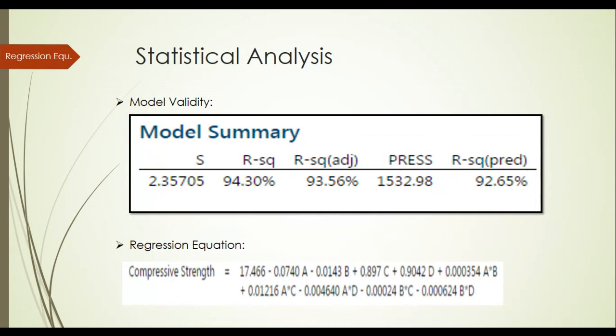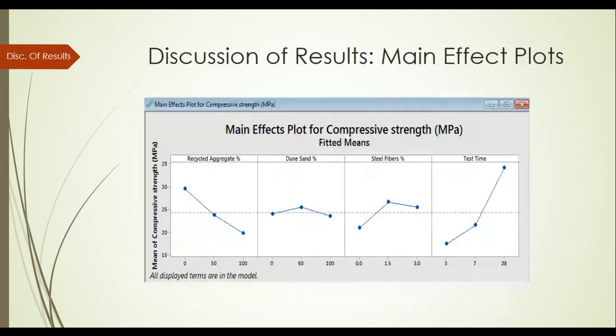Okay, and for the final model under the full factorial design, we have ended up with this model where A is the recycled aggregate, B is the dune sand, C is the fiber contents or percentage, and D is the time to testing. Here is the final model based on the full factorial. As we see here, the R squared value is high, 94.3, which is a very good one.